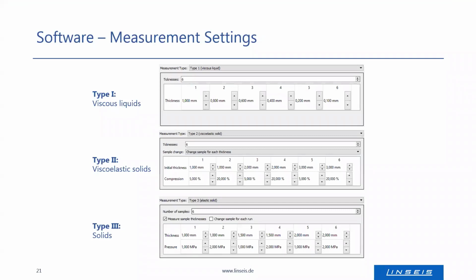The measurement settings done in the software differ for each sample type. For type 1, the viscous liquids, one needs to define the thickness. As mentioned before, one needs at least 3 different thicknesses to obtain a good linear fit in the diagram of thermal impedance dependence on sample thickness.